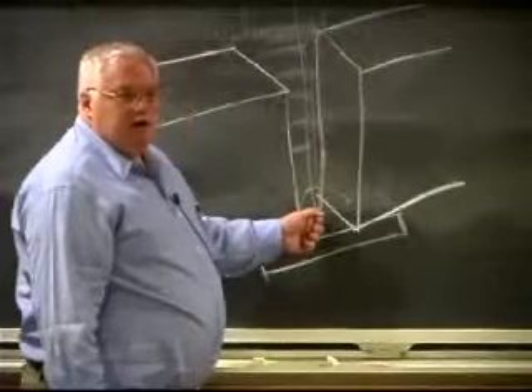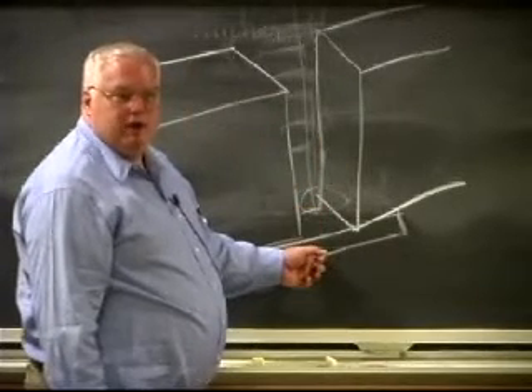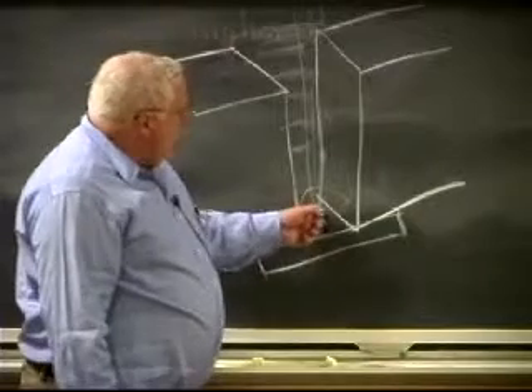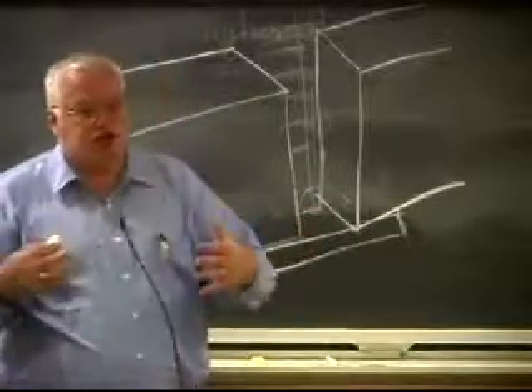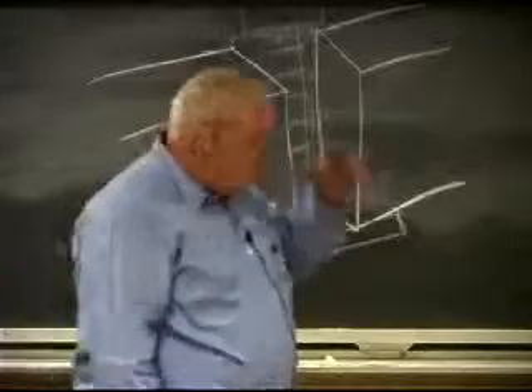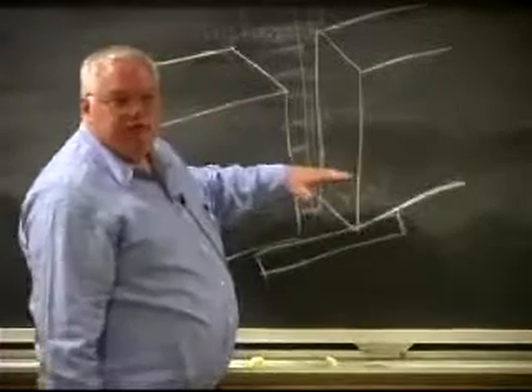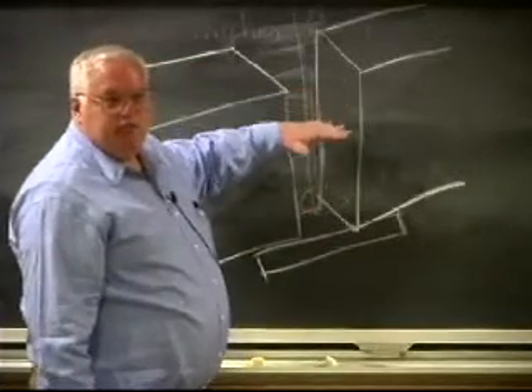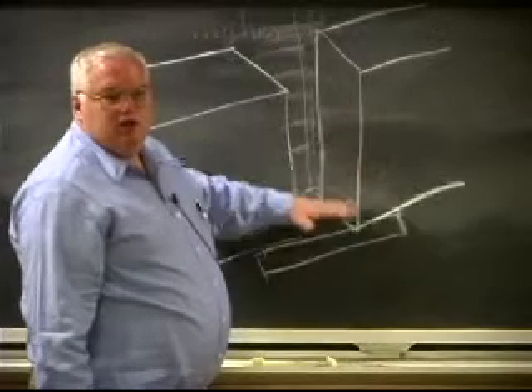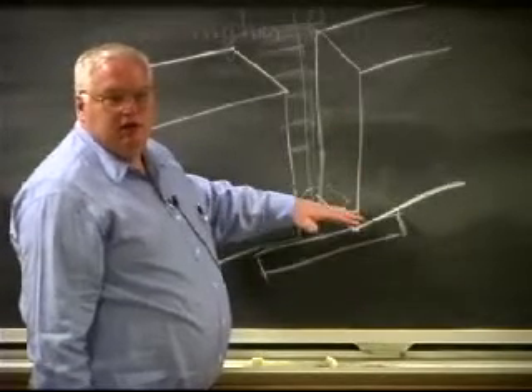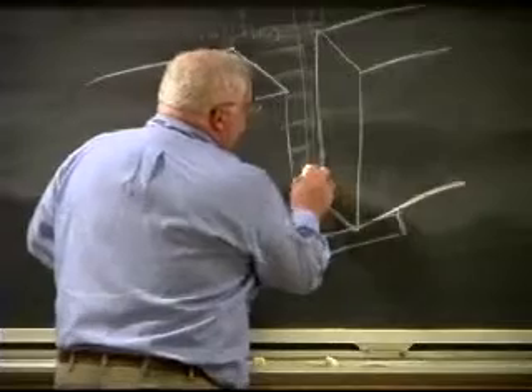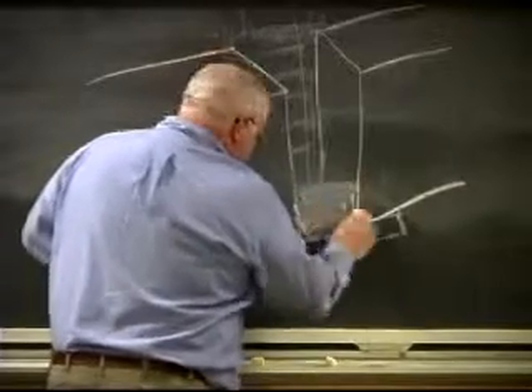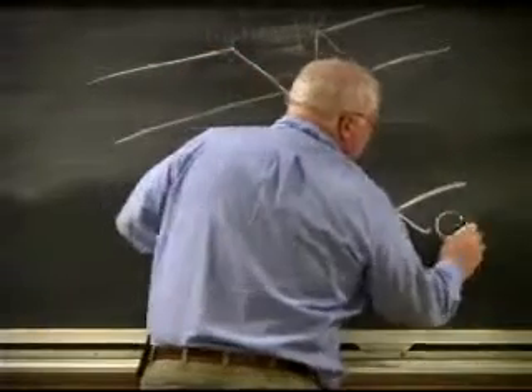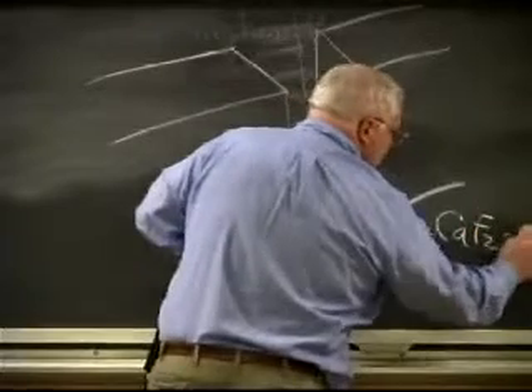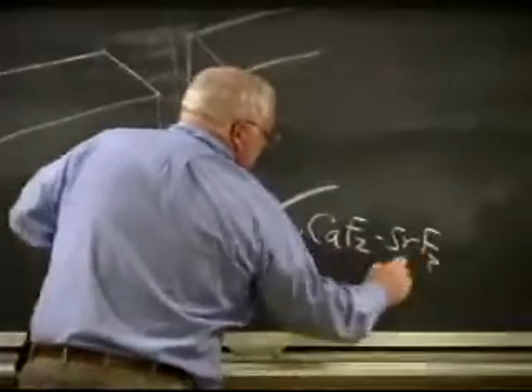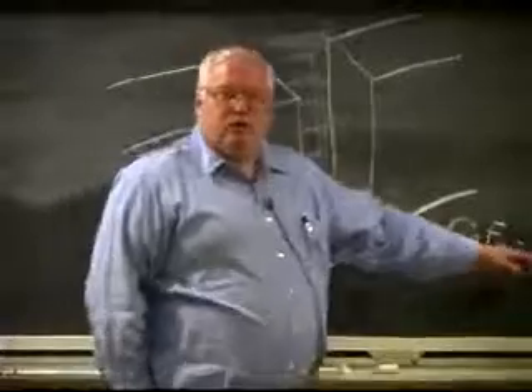I strike an arc down here on this consumable base plate that I'm going to cut off later. That arc melts everything just like in the submerged arc process, although in this case I put a high enough head of flux that the glassy molten flux layer collapses the arc. It's too heavy for the arc. And now I have a layer of molten slag. In this case, for titanium, it tends to be calcium fluoride and strontium fluoride mixtures, because those are the highest melting fluorides.